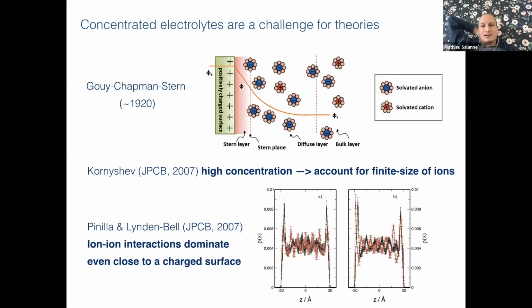And so this was more or less known since a long time, but it was more formulated in 2007 by Kornyshev, who showed that you need to account for several effects at high concentration in analytical models. And then there were the first simulations by Ruth Lynden-Bell in Cambridge, who showed that you have very strong cation and anion interaction at the surface in ionic liquids. And so this picture cannot be used anymore.